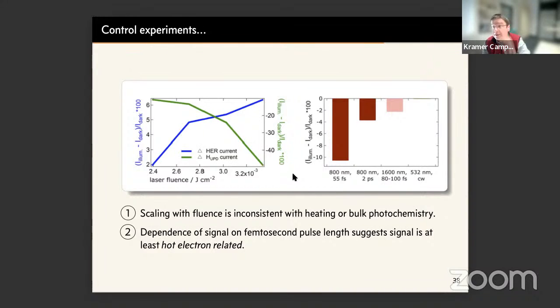So what I want you to conclude from this is that this scaling is two things. The first is that the plot on the left suggests the scaling with fluence is inconsistent with heating or bulk photochemistry, right? This kind of saturation is not what you would expect if either of those two things were happening. And that this dependence of the signal on the femtosecond length of the pulse suggests that whatever this thing is at UPD potentials, it is at least hot electron related.